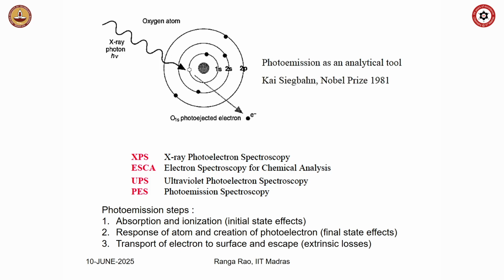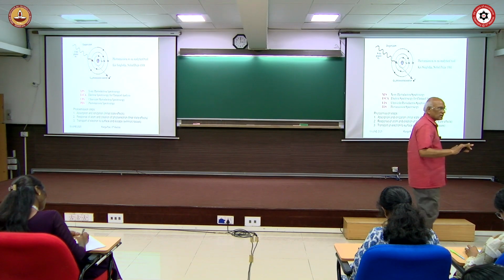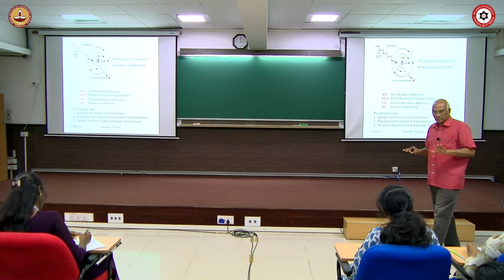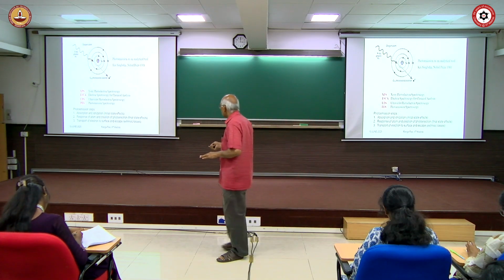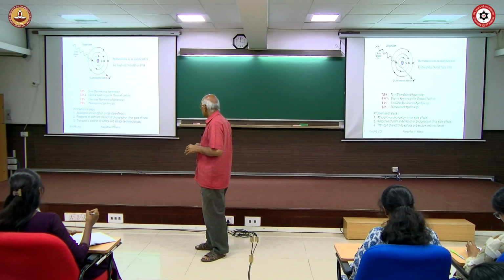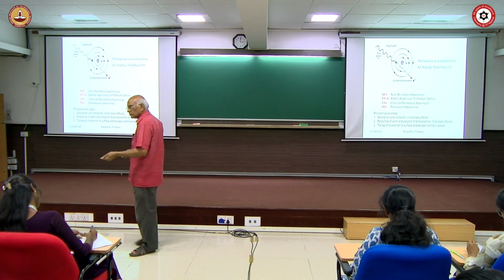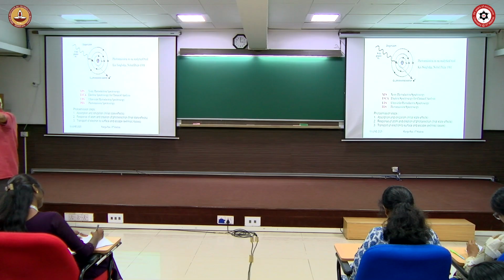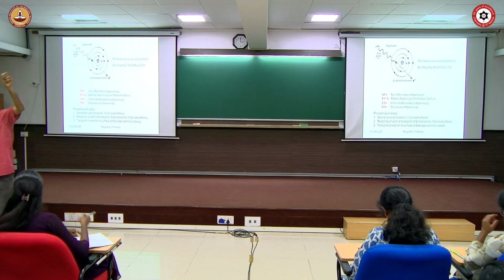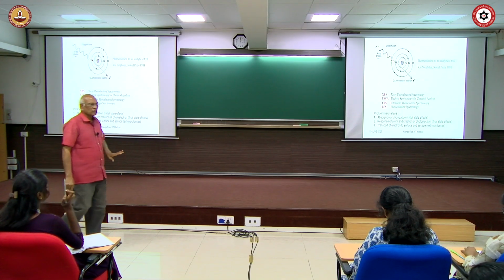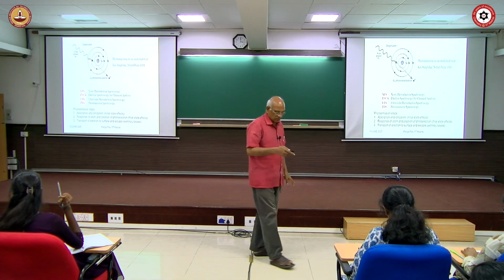But there are 3 steps involved in this. Absorption, ionization, the initial state effect, response of the atom, and creation of the photoelectron, that is the final state, and then transportation of the electron from the place where it is ionized to the surface, and then escape. We are now talking about the photoemission spectroscopy of solids. Photoemission spectroscopy of gases is different, that we will come to a little later. When the electron is transported from the place where it is ionized to the surface, it can come out from the top layers, about 100 angstroms, without losing energy. But if it is coming from deep, it tends to lose some energy. That will constitute the background in the photoemission spectrum.